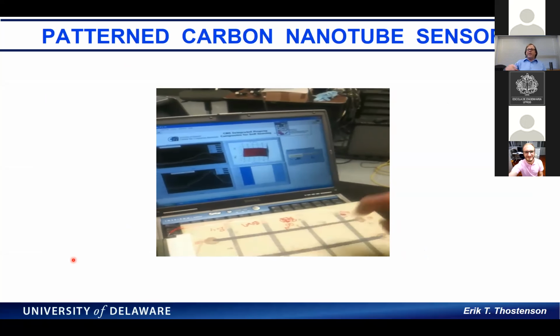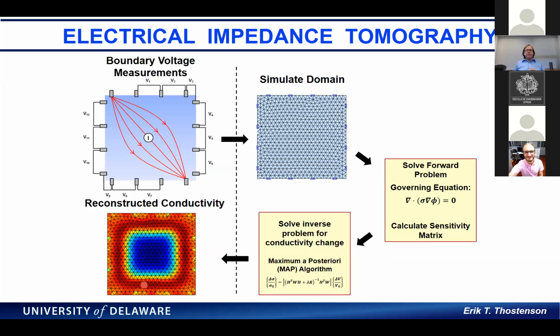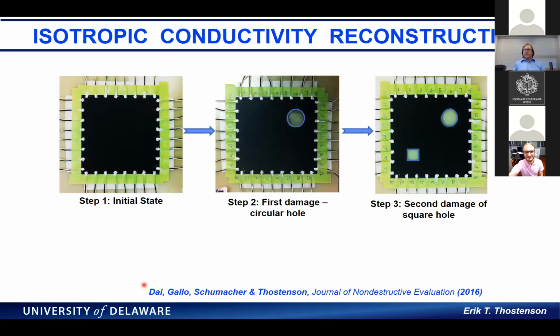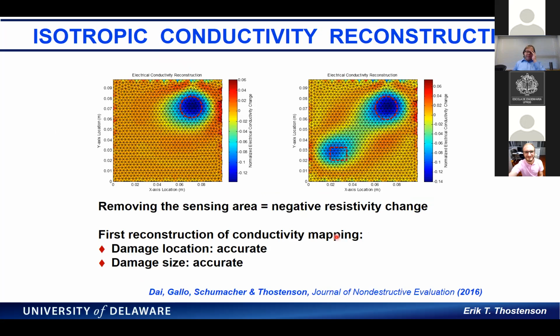So of course, one of the things we want to know is not just that there is damage, but where is that damage? And this approach we use is electrical impedance tomography. And I won't spend a lot of time talking about the theory, but essentially what we're doing is we're measuring boundary voltage around the corners, and we're injecting a current. And then from that data, you simulate the domain, and then you solve the inverse problem, and you reconstruct a conductivity map. And so this was some of our initial experiments where we looked at a panel that we manufactured, and then we just introduced different types of damage. And again, the reconstructions were quite accurate. The damage location and the damage size was quite accurate based on this carbon nanotube composite.